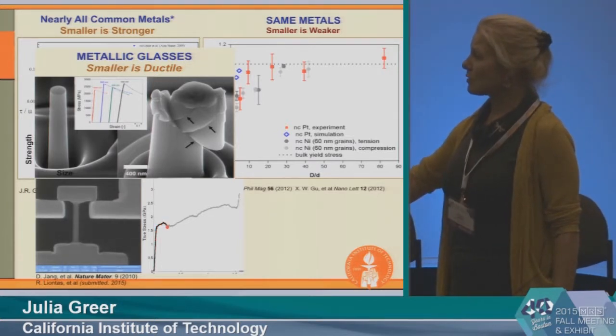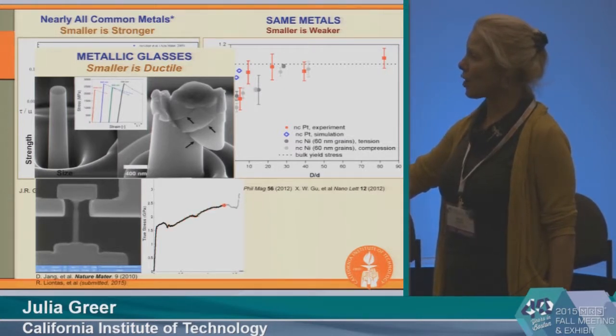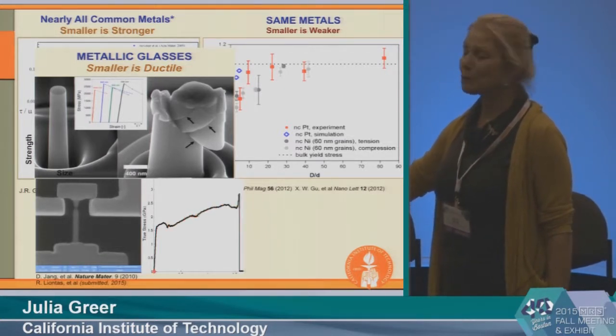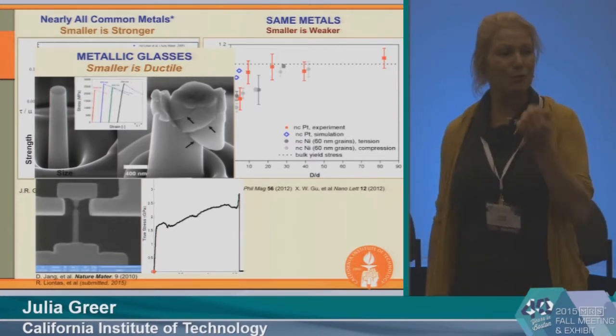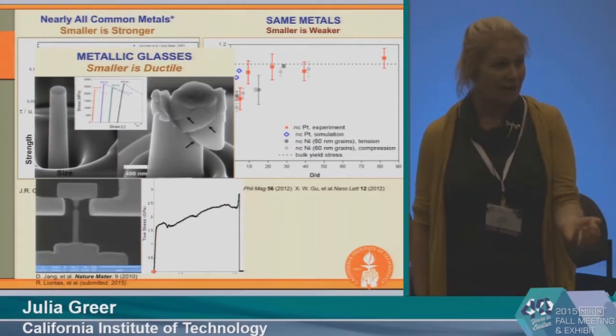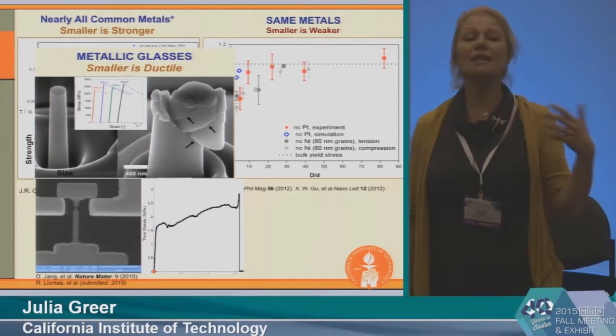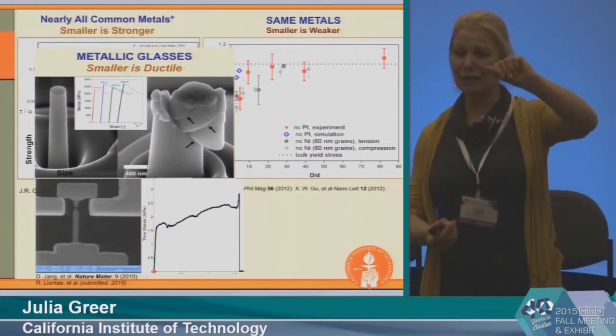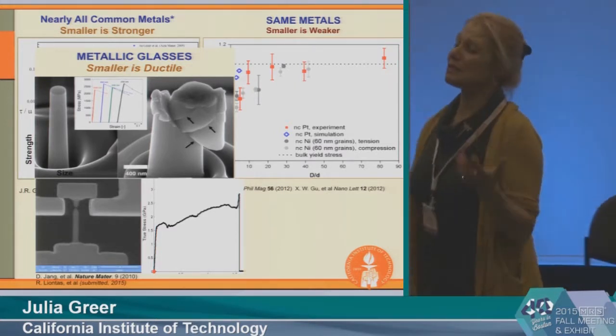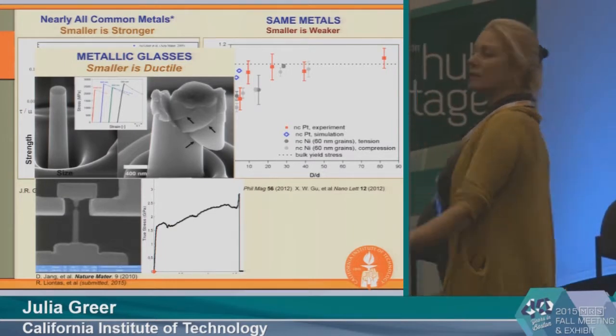So this is a stress-strain type of data. So this is strain, and right here is 100%. So you can see that this particular glass fiber was able to deform by 100% before failing. So this would never be possible at the macro scale. If you look at a glass fiber, this would never happen. So materials that are intrinsically brittle can be made ductile by virtue of the size reduction.